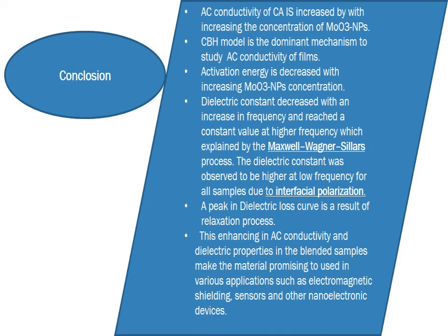Conclusion: AC conductivity of cellulose acetate is increased by increasing the concentration of molybdenum trioxide nanoparticles. The correlated barrier hopping model is the dominant mechanism to study AC conductivity of the films. Activation energy is decreased with increasing molybdenum trioxide nanoparticle concentration.